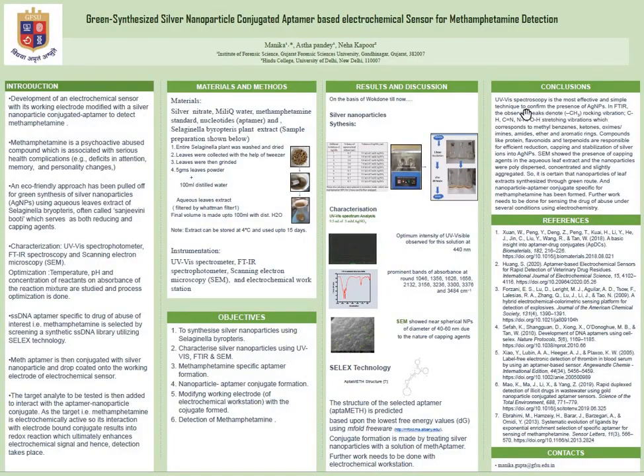So finally it can be concluded that UV-Vis is the most efficient technique to confirm the presence of AgNPs at the initial stage, and then FTIR also showed peaks that indicated the presence of compounds like proteins, flavonoids and terpenoids, which are responsible for reduction, capping and stabilization, and SEM also showed the presence of capping agent in the extract. Also nanoparticles were polydispersed and concentrated and slightly aggregated.